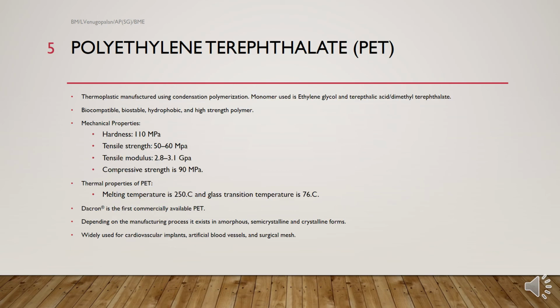The next one is PET, which is polyethylene terephthalate, the last polymer that we are going to see in bio-non-degradable polymers. These are thermoplastics manufactured using condensation polymerization. The other two are addition polymerization; this one is condensation polymerization. The monomers are ethylene glycol and terephthalic acid or dimethyl terephthalate. It is biocompatible, biostable, hydrophobic, that is, it does not like the presence of water, and a high strength polymer. The hardness is 110 megapascals, tensile strength is 50 to 60 megapascals, tensile modulus is 2.8 to 3.1 gigapascals, and compressive strength is around 90 megapascals. The thermal properties of PET include a melting temperature of 250 degrees centigrade, which is very high, and a glass transition temperature of 76 degrees centigrade.